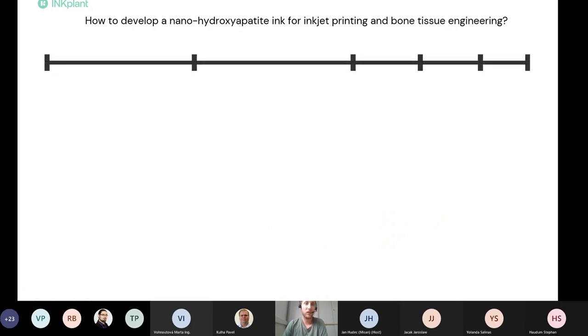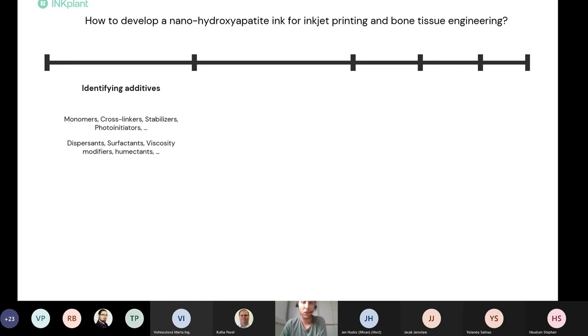The development process of an ink formulation starts by first identifying certain additives that can be used. For example, if we talk about photopolymers, we need certain monomers, cross-linkers, stabilizers, and photoinitiators. When it comes to developing nanoparticle-laden inks, you need a dispersant to prevent the nanoparticles from aggregating within your ink, certain surfactants to tune the surface tension to the desired range, certain viscosity modifiers, and humectants to tune the viscosity.